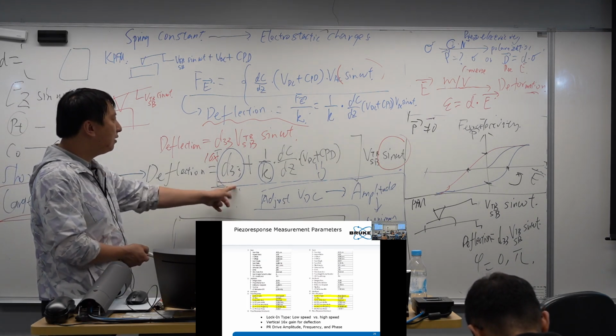So once it's enabled, your signal is magnified by 16. If some of you want to do a quantitative study to get the D33, please remember to reduce the signal back by the factor of 16. Okay, so that's the workspace.